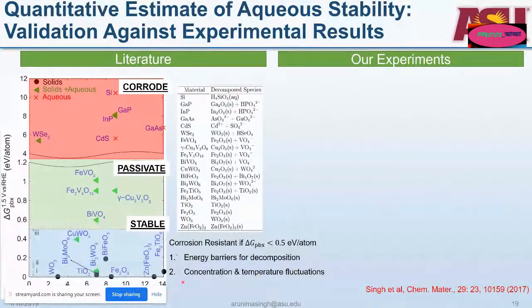And for the phases which were reported to passivate, we found that our predictions of what the Pourbaix stable phases or the decomposed species would be matched with what was reported in the experiments. For instance, for FeVO4, those reports say there's perhaps iron oxides on the surface. So we found a very strong validation of our work by looking at the literature, but of course the literature